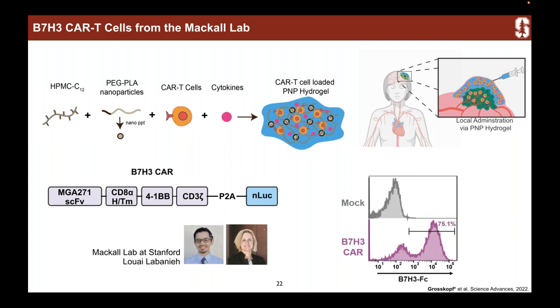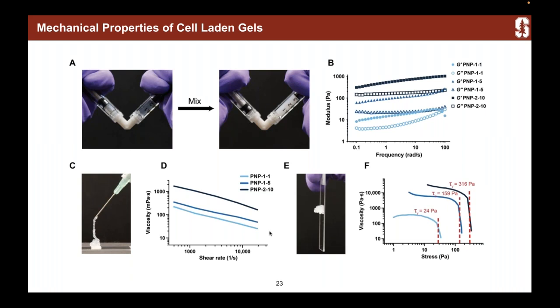We injected these hydrogels next to solid tumors to see if delivering them locally in this hydrogel niche could improve tumor treatment. We worked with the Mackall Lab at Stanford to make the CAR T cells. In this project, I was loading about 20 million cells per mL in the hydrogel material. I ran rheology on the cell-laden hydrogels, and even when encapsulating these high numbers of cells, we could measure the viscosity using our viscometer — and the viscosity barely changed from what we see without cells, really insignificant differences.